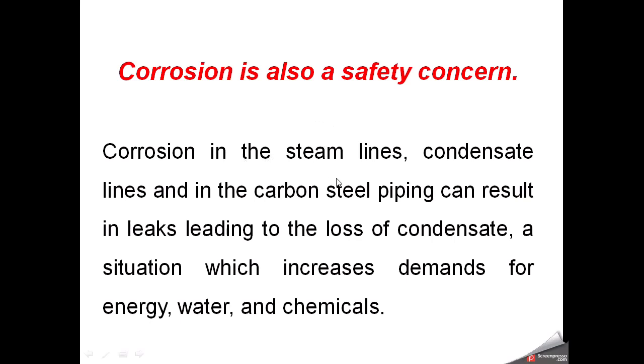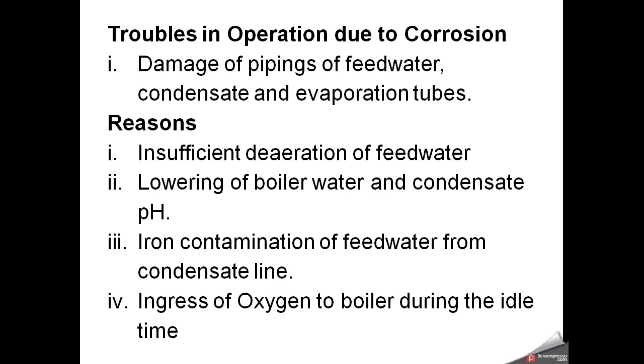Corrosion in the steam lines, condensate line, and in the carbon steel piping can result in leaks leading to loss of condensate, a situation which increases demand for energy, water, and chemicals, and outage of the plant as well. So if we summarize this, troubles in operation due to corrosion are basically damaging of pipes of feedwater, condensate, and evaporation tubes. And what are the reasons? Insufficient deaeration of feedwater. If we do not properly apply deaeration, dissolved gases will come into the water and start corroding the lines. Lowering of boiler water and condensate pH, because at low pH it becomes acidic and it will affect the metal piping.